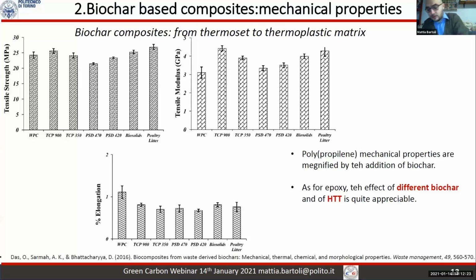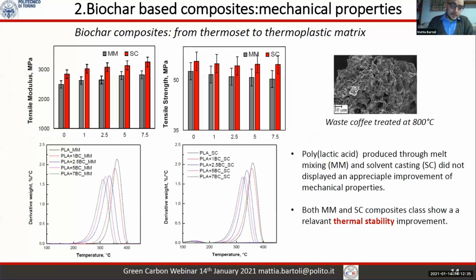But for thermoplastics, the way of production is also important. We tested several of them. Here you can see melt mixing and solvent casting results. In this case, by using PLA and waste coffee derived biochar, the picture on the right, you can see the mechanical properties are not so enhanced by the addition of biochar, but the thermal stability is greatly enhanced. And this is very important for an application that you will see in the next slides.